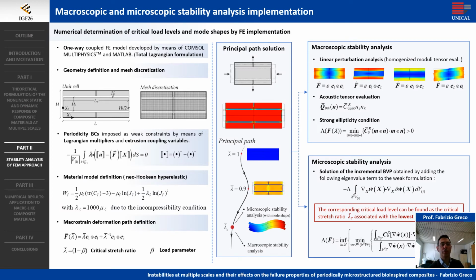The numerical determination of the critical load levels and the associated mode shapes has been carried out here by using a one-way coupled total Lagrangian finite element formulation, able to determine the principal solution path for the analyzed unit cell assembly in coupling with the accompanying eigenvalue boundary value problem, giving the instability critical load levels in a sequential way. The geometry of the analyzed two-dimensional unit cell refers to a typical nacre-like material and is formed by reinforcement in the form of stiff platelets embedded in a soft matrix material and arranged in a brick-mortar pattern.